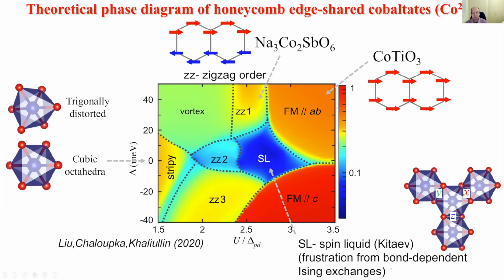So for the Kitaev spin liquid, you need the Ising axis to rotate with the bond. So to be very close to the cubic symmetry. And in fact, this work up here gives as much insight as can be obtained at this point from this phase diagram. And we've used exactly the same spin orbital exchanges as they propose. And there's a mechanism from these spin orbital exchanges to project, in this blue region, to something that's predominantly the Kitaev Hamiltonian. That's why this phase is stable in that region.